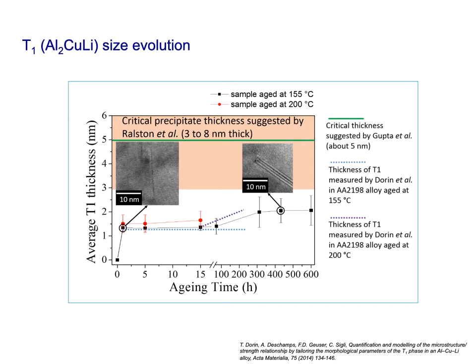compared to the thresholds that were set by Rajiv Gupta and co-workers of about 5 nanometers, given by that green line from work on 7000 series alloys, and the orange range that was determined by Kevin Ralston for 2000 series alloys, largely aluminium, copper, magnesium alloys, which shows a range of about 3 to 8 nanometers there. And so you can see we never really get to that critical thickness, and that's a way that we can rationalize the high corrosion resistance that's afforded in this particular alloy.